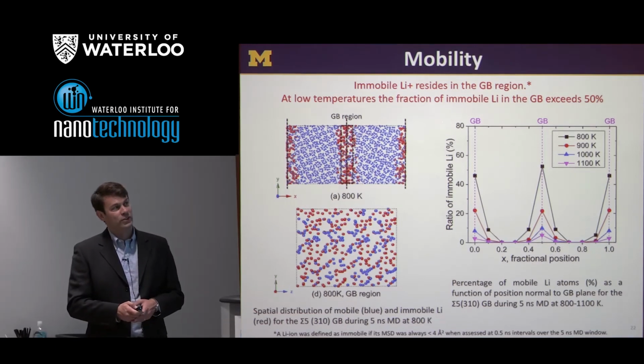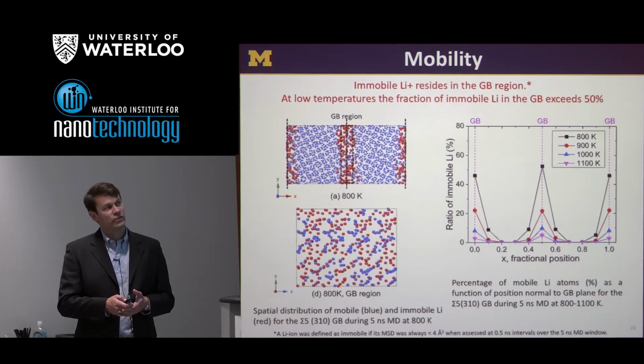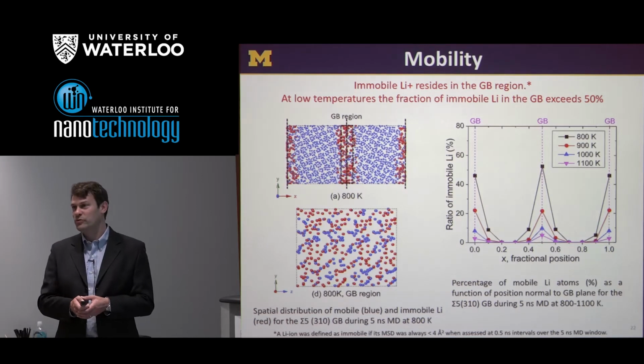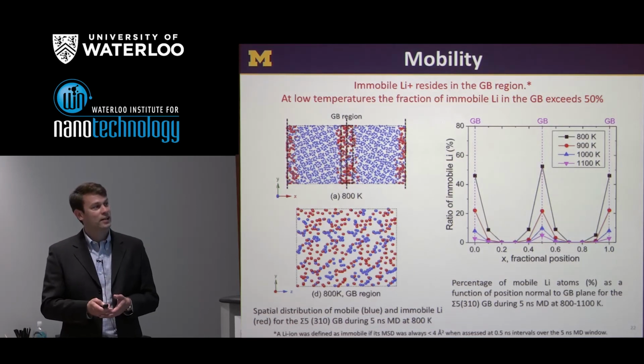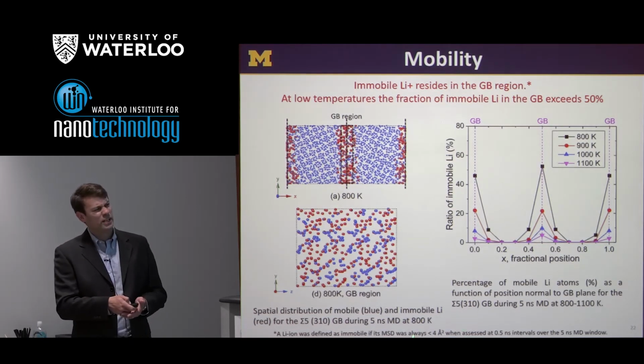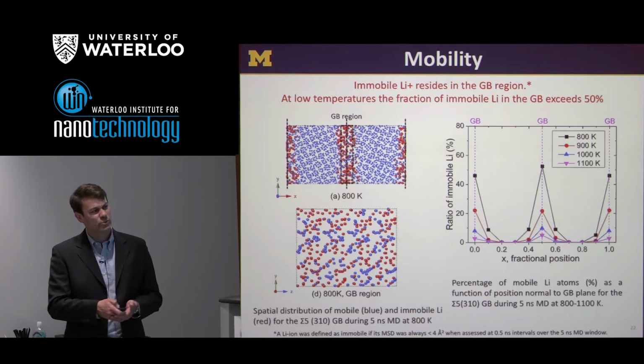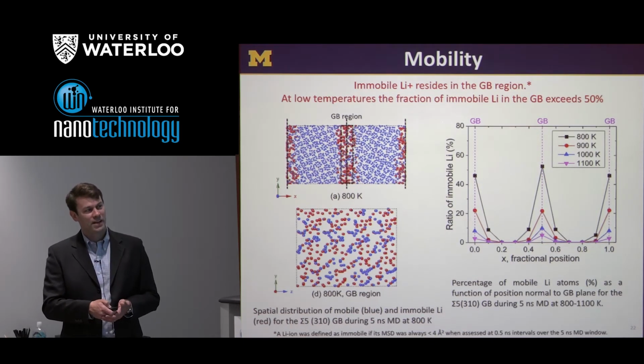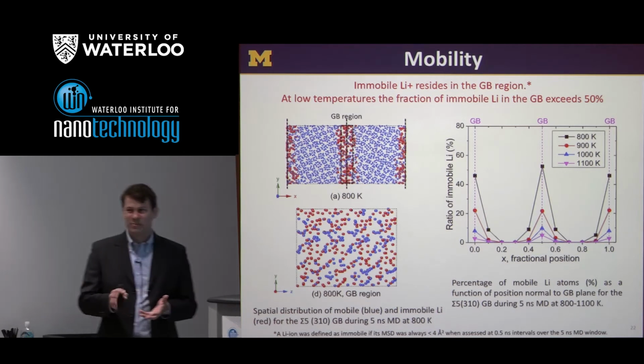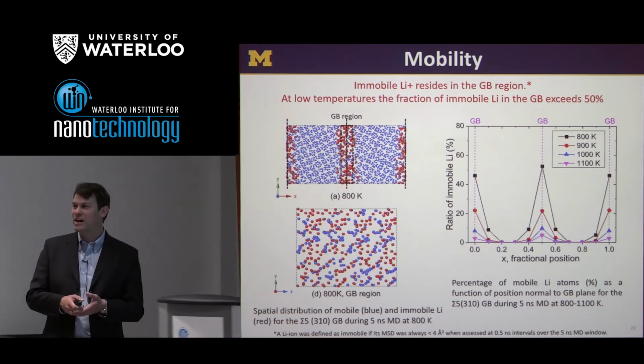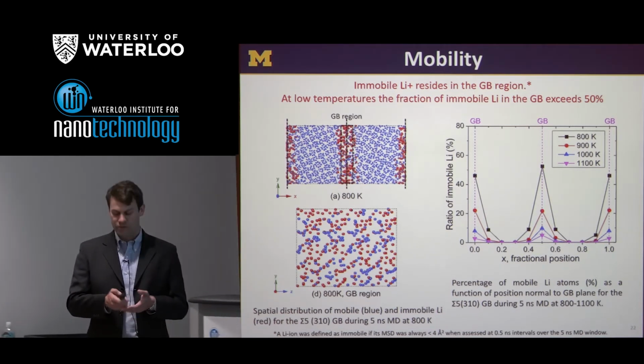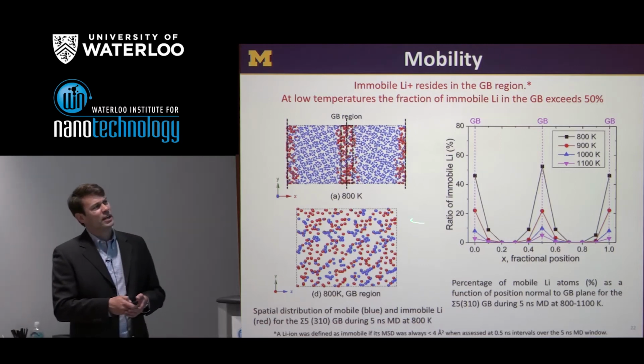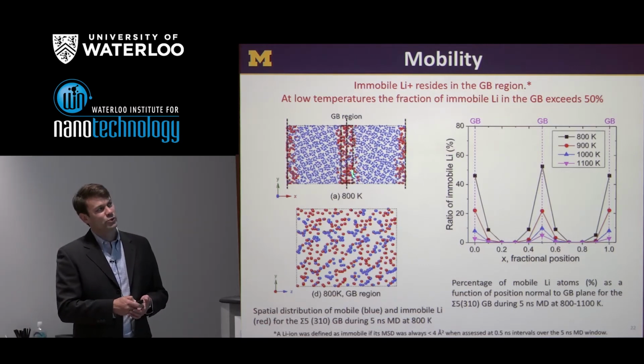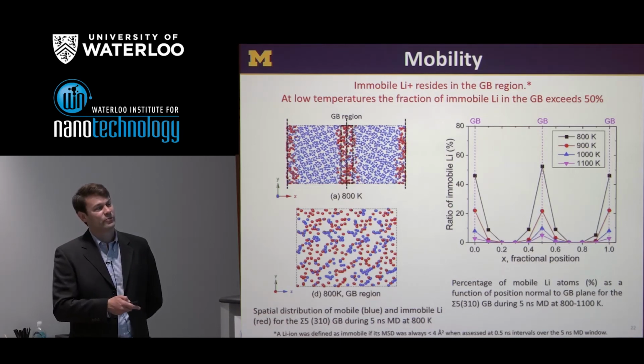We can also look at this using an equivalent technique where we just highlight the lithiums which are moving less than a certain mean square displacement. Here we've picked a value of less than 4 angstroms squared in any half a nanosecond interval. This is roughly about the 15th or 20th percentile of the displacements of all of the lithium in the cell. And what you can see is, those atoms which are limited in their mobility, I've colored here in red, and those are all concentrated on the grain boundary region.